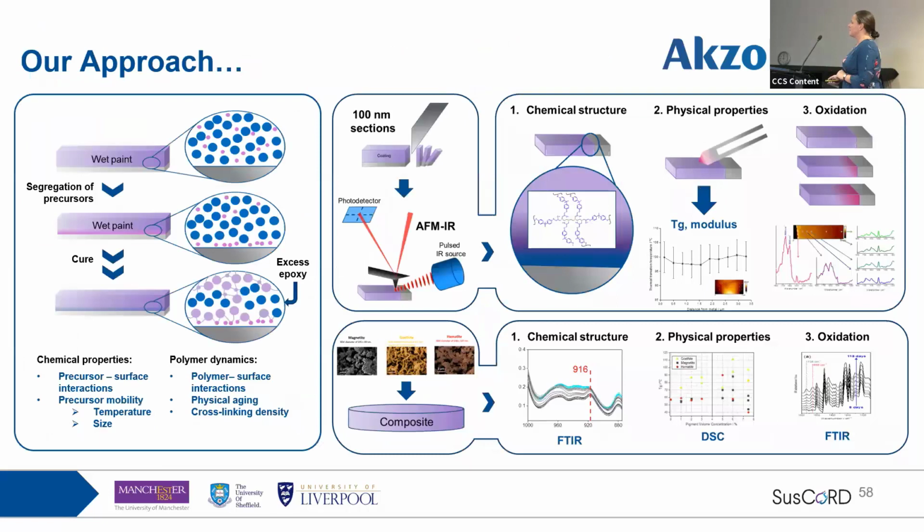So we've come up with a different approach. I'm really focused on the AFM-IR technique generally. To investigate the chemical structure near to this interface directly, we take a thick coating and section it using ultramicrotomy. And then we can look at that interface directly using AFM-IR.